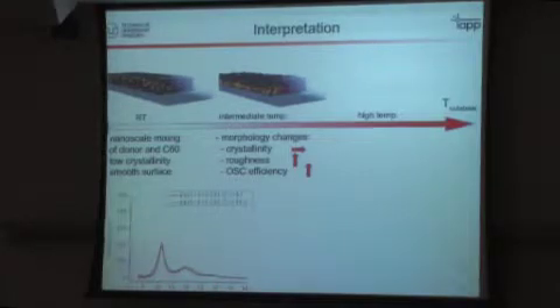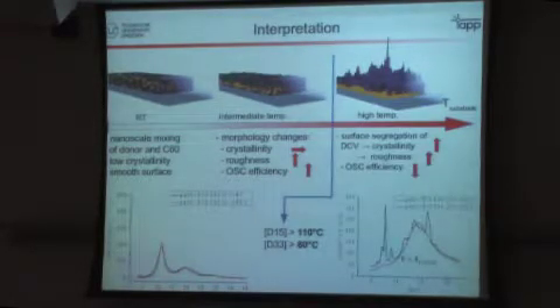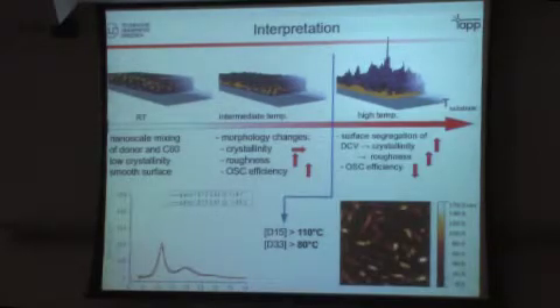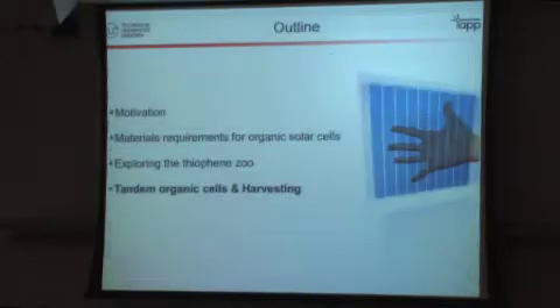At the same time, the films start to become rough. And at the highest temperature, the films themselves were so rough that they couldn't be used for devices anymore, and the efficiency then goes down very quickly when you exceed a certain temperature. We could actually show that at very high temperatures you were seeing these worm-like crystals, which were pure thiophene, growing out of the layers and forming crystals on top of the bulk heterojunction. So the dynamics of this bulk heterojunction formation is a very complex function of temperature.